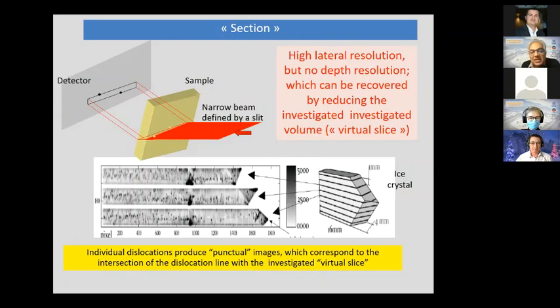For instance, for an ice crystal, where we looked at several sections like that, the sections appear here, and you see a lot of small points in the section. These small points are individual dislocations which produce a punctual image, corresponding to the intersection of the dislocation line with the investigated virtual slice. So you have, in addition, depth resolution by using this technique.